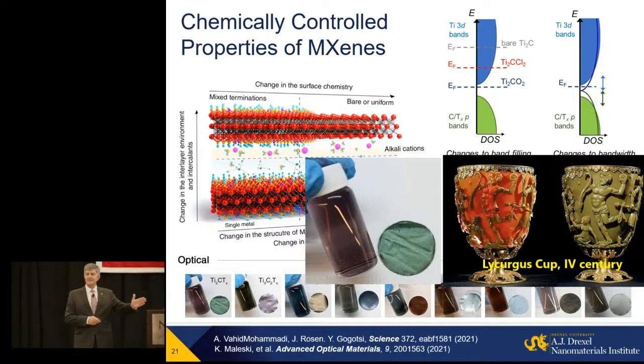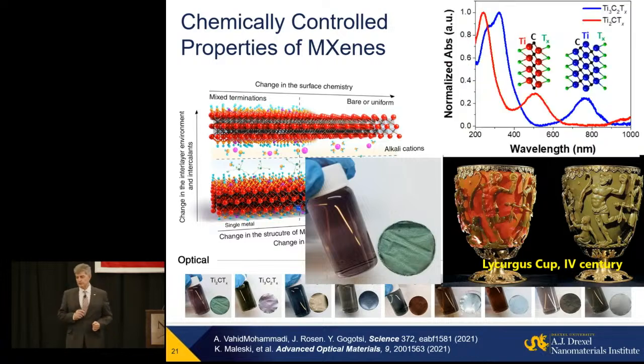Moreover, we can apply a small potential, and we can shift the absorption peak by about 100 nanometers in titanium 3C2, by 200 nanometers, making it also electrochromic. So this is just an example of how we can control and modulate the properties to achieve what we need here.